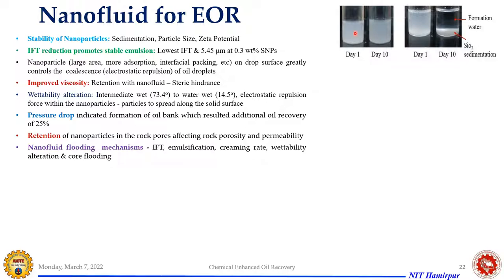we have seen how these nanoparticles, which have high surface area, could accumulate more of the surfactant at their interface, including polymer. So that's why their electrostatic interaction forces are reduced. In fact, the electrostatic repulsion forces are enhanced, and that's what you can see. There is negligible or minimum sedimentation behavior that we have seen here. As visual observation of sedimentation is not a correct method, in the same pattern we have done sedimentation analysis followed by particle size analysis and zeta potential analysis, to see how stable these are. Exploring all these properties, we have identified that the nanoparticles were stable in the chemical phase.